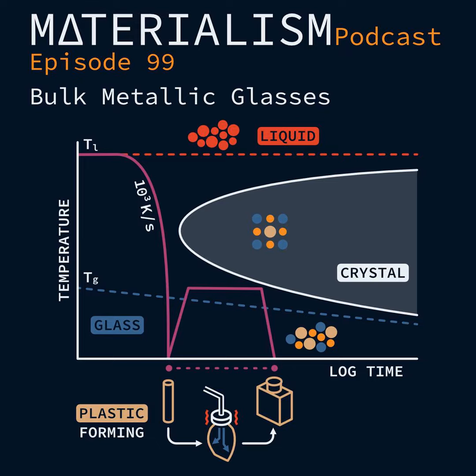Bulk metallic glass is referred to as such because before, the samples had to be very thin. We talked about beating this time scale of crystallization. And the way you beat it is you have to take the heat out very quickly, so you have to cool them very fast. The thinner the sample, the shorter the diffusion path for heat is, and the faster you can cool them. So they observed that they could make samples in bulk form, which they arbitrarily defined to be 1 millimeter, as a true bulk. So even for these very thick samples, or in other words, for very long times or slow cooling rates, they can form these glasses. So that happens in the 70s.